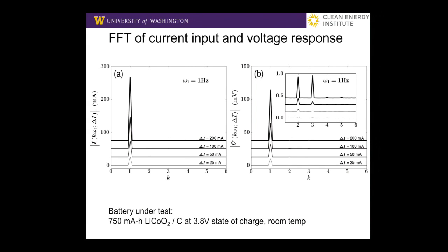So here's what it looks like if we take a lithium-ion battery. It's a 750 milliamp hour lithium cobalt oxide battery with a carbon negative electrode, held at a 3.8 volt state of charge for that battery, room temperature, and we modulate the input current. And here I'm showing the magnitudes of the current, of the transformed current, as a function of K, the harmonic number. This is for an input frequency of 1 hertz. So we're oscillating the current at 1 hertz, and the current comes in.